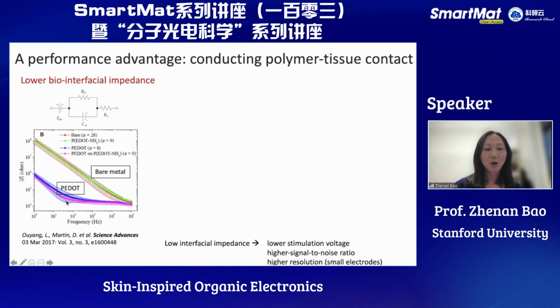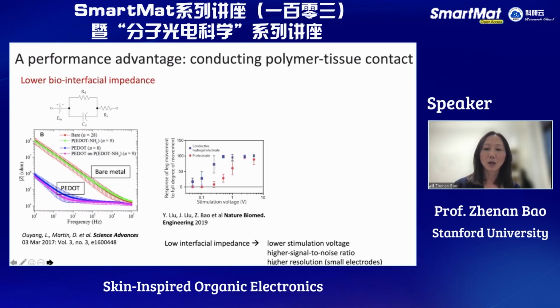But for conducting polymer, because of its high capacitance characteristic due to its high porosity, as well as the ionic conductivity, it has been known that conducting polymer has several orders of magnitude lower impedance at the interface with biological tissue compared to that of metal electrode. So this is really important because that can lead to lower stimulation voltage.